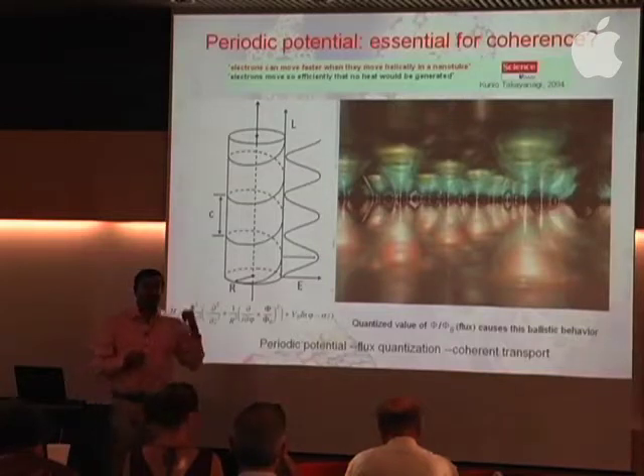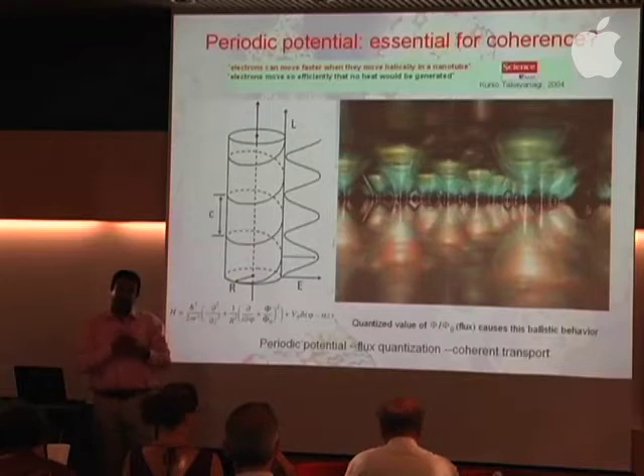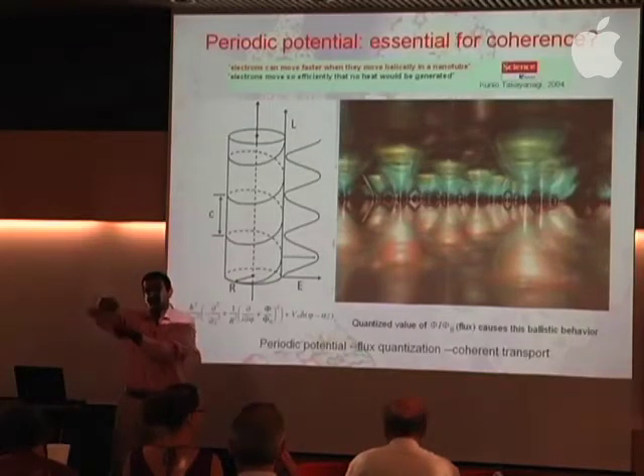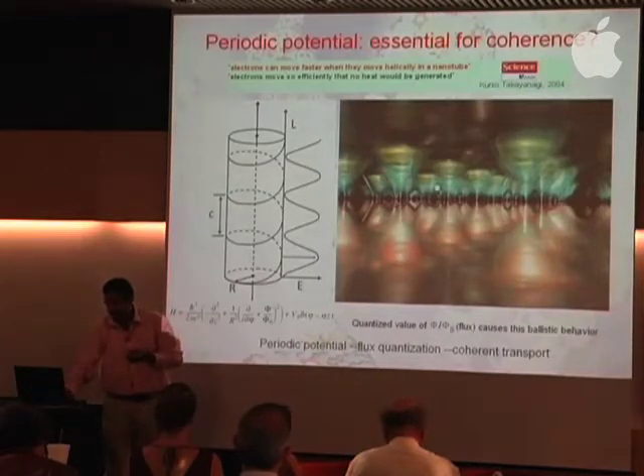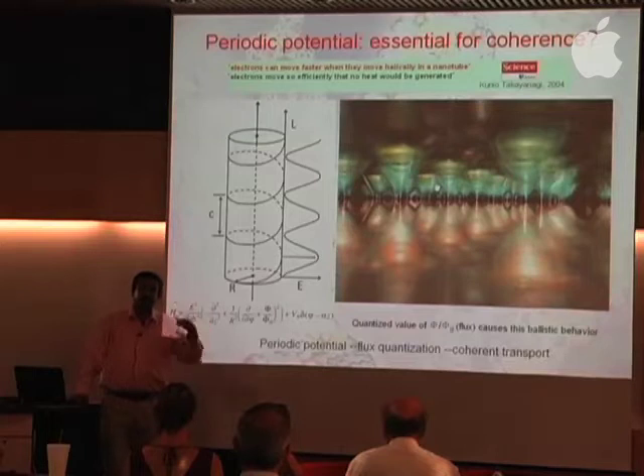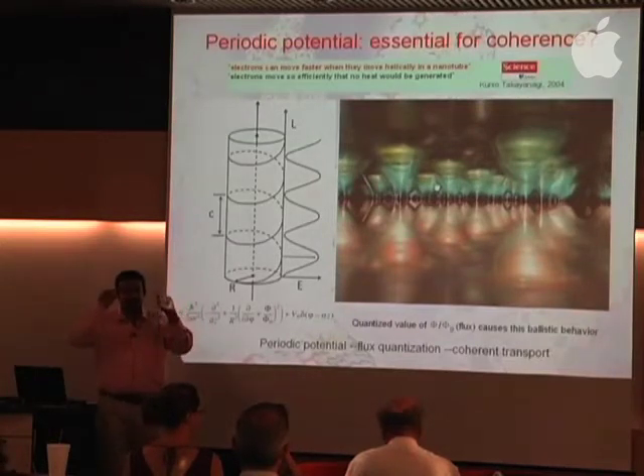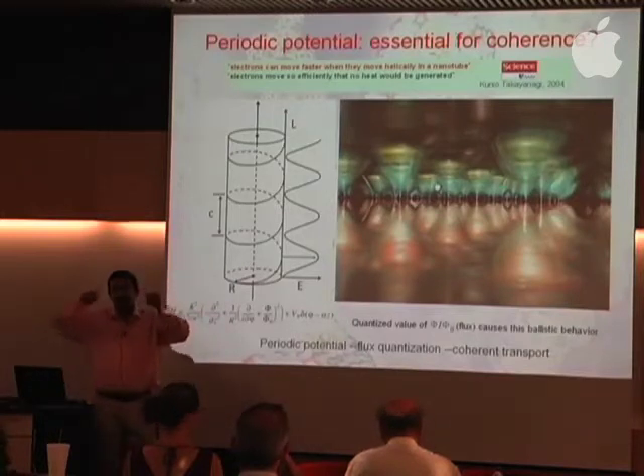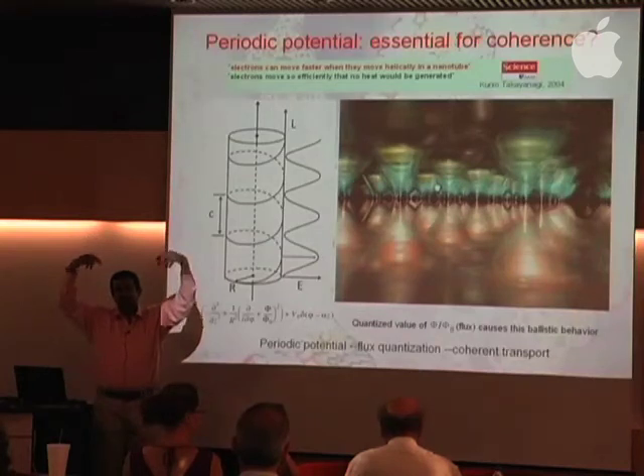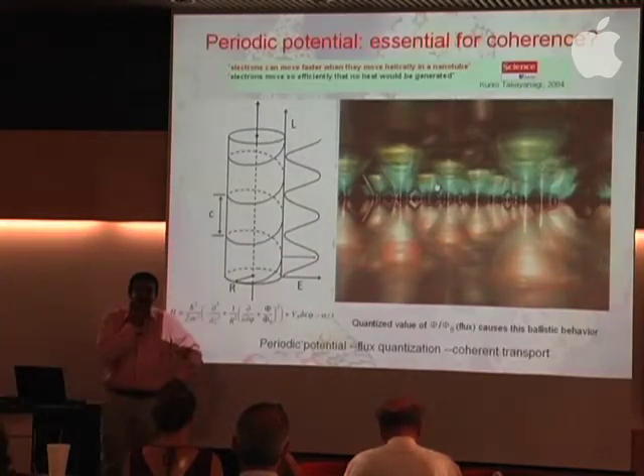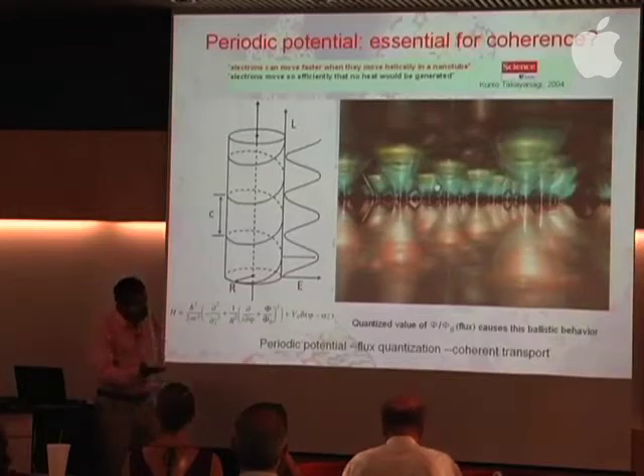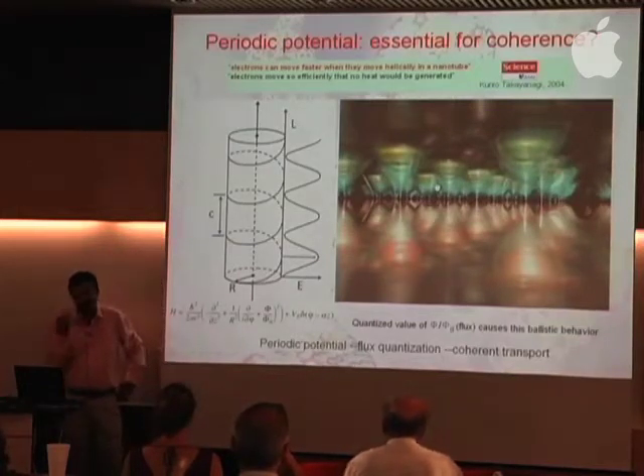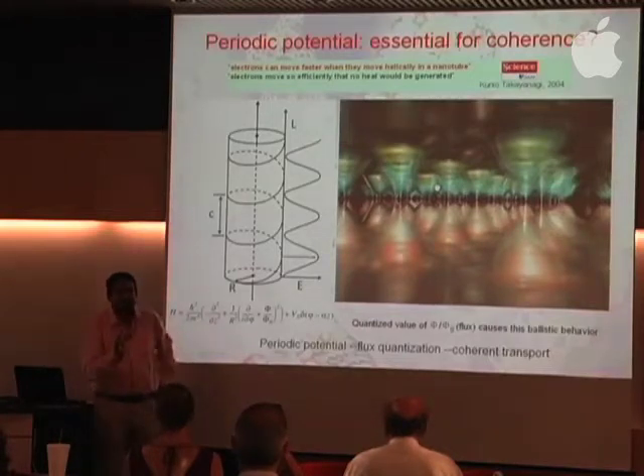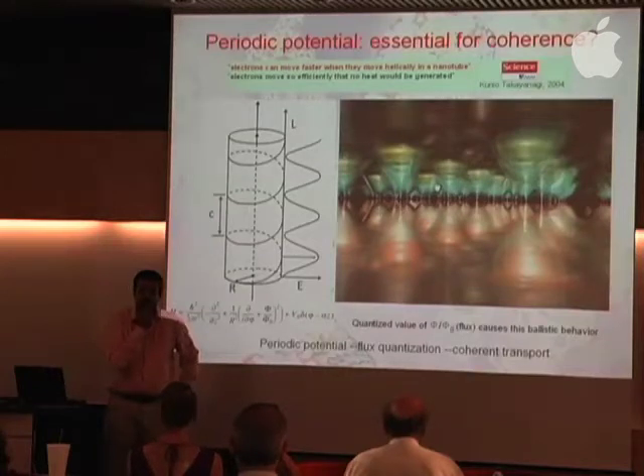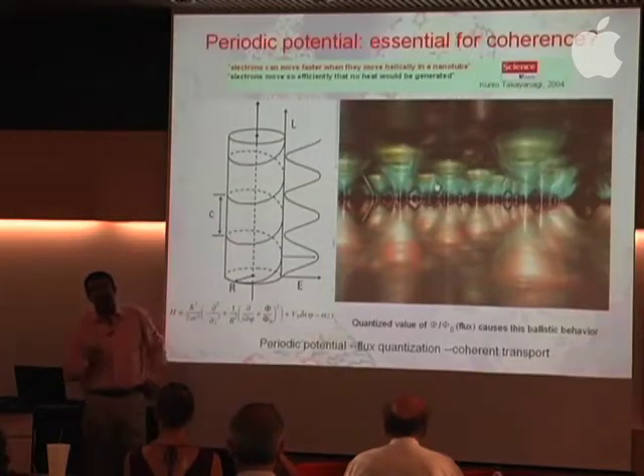Now, as soon as we come to the helical potential, or periodic potential helical path, you will find that there is a point contact gap in the band energy diagram. What happens is that if you pump electrons into the system, they store at the conduction band edge, and all of them are triggered together. That makes it coherent. Kunio Takayanagi's Science paper is very, very famous. What did they do? They took a gold nanowire and made a spiral. When they did temperature variation, they found ballistic transport, meaning quantum mechanical transport was going on in the system, and at the same time they found it is independent of temperature.